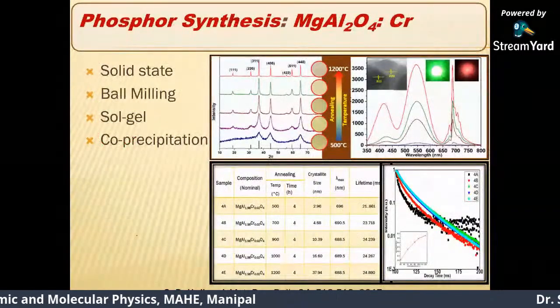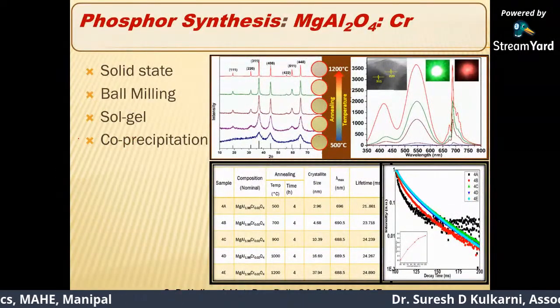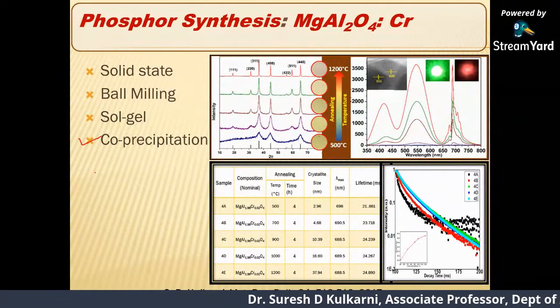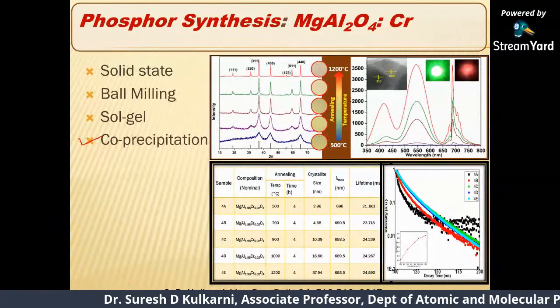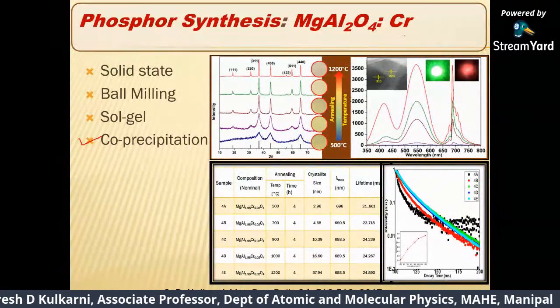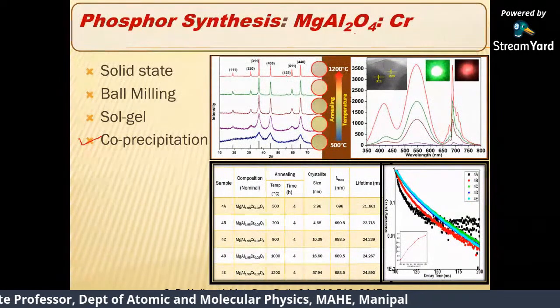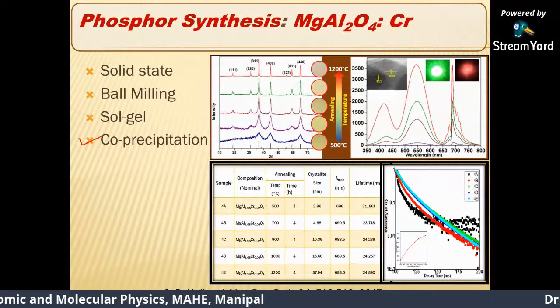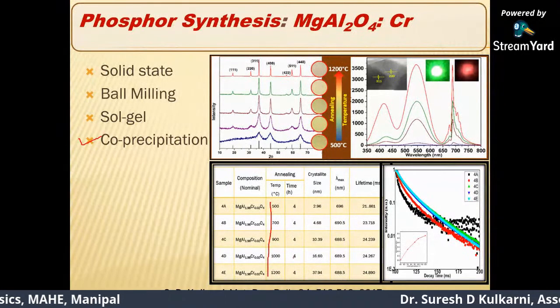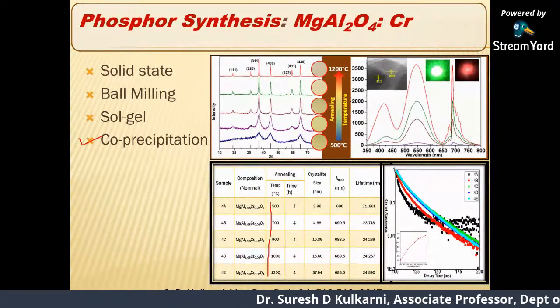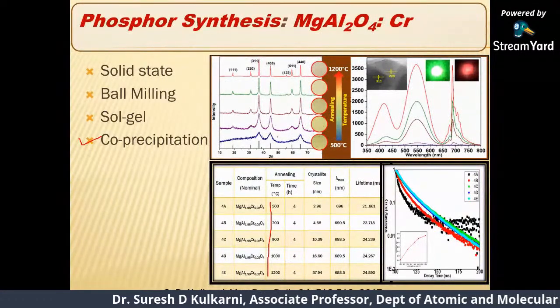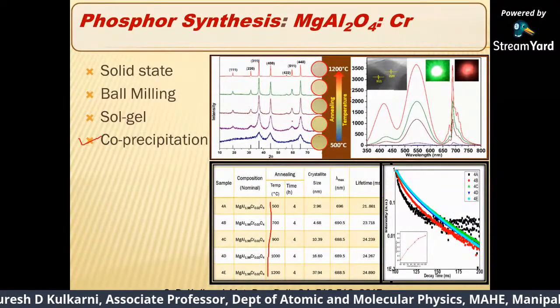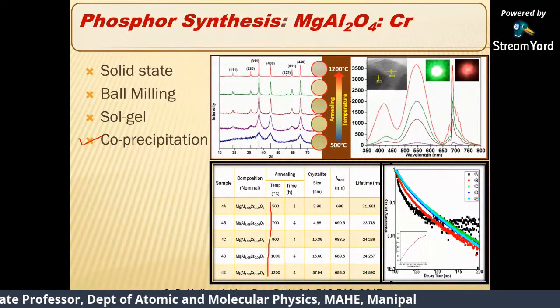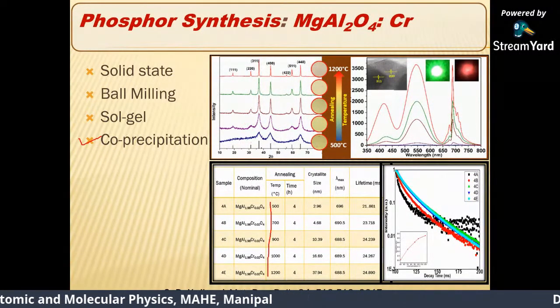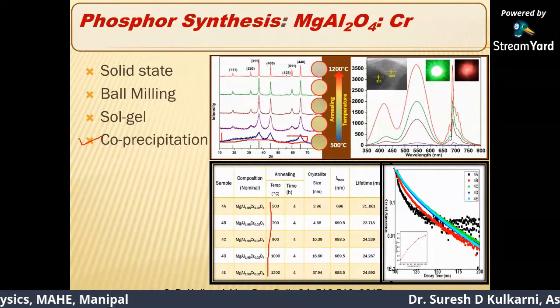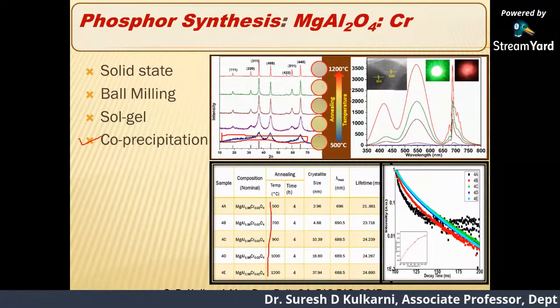So what we did is we used a simple co-precipitation approach, just to understand initially when we started working, what is the time taken for synthesizing one phosphor, a chromium doped magnesium aluminate. We synthesized the material, and you can see the material is heated to different temperatures from 500 to 1200 degrees Celsius, and you can see the XRD pattern. A proper phase is formed only at a temperature around 700 degrees and above. You can see it is mostly amorphous here. The peaks are not well defined, all the peaks are not identified.